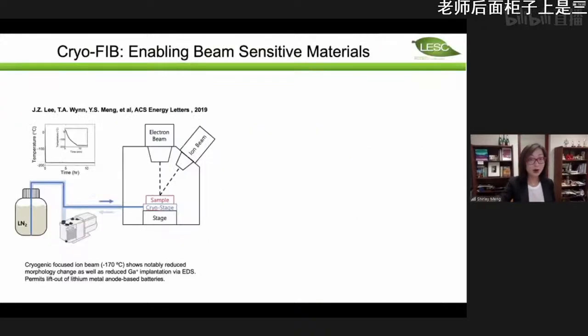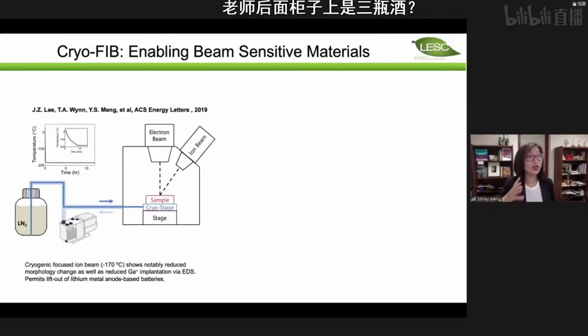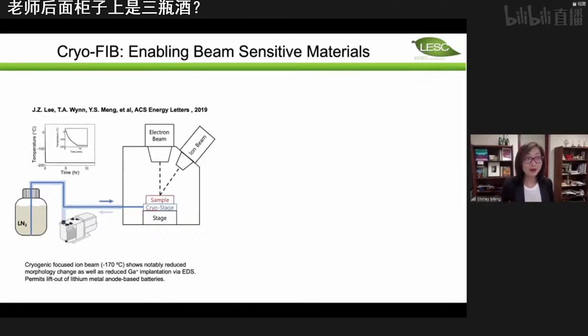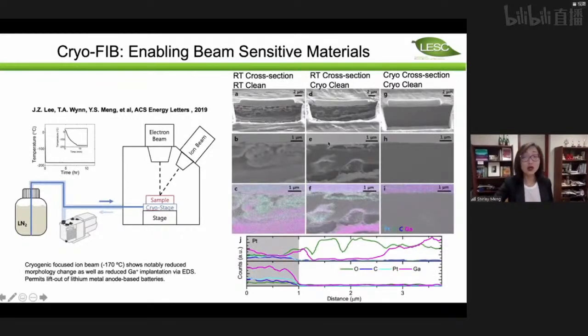So I'll show you an example. Literally, lithium reacts with everything. When I say everything, it means nitrogen, oxygen, carbon dioxide, water. So when we do scientific instrument work, even if you use the focused ion beam to try to cut a fresh surface of lithium, the gallium ions actually alloy with lithium at room temperature. So if you do a room temperature cut of the lithium surface, everything you see here is artifacts. It's not the lithium surface that you're seeing.